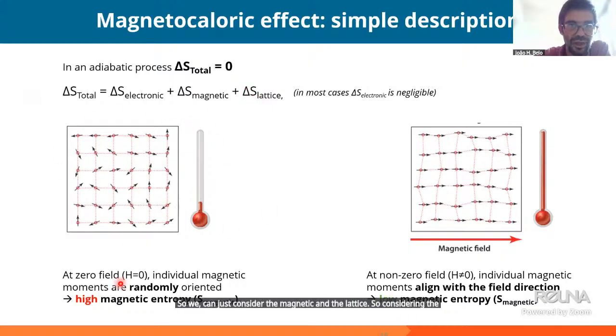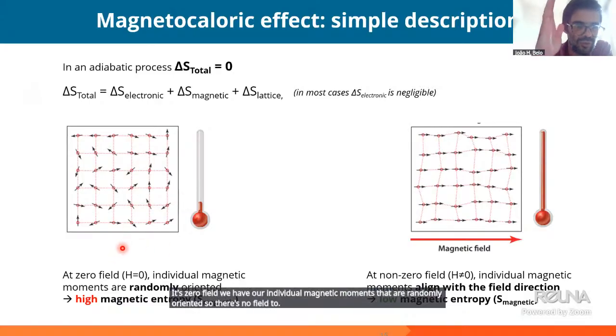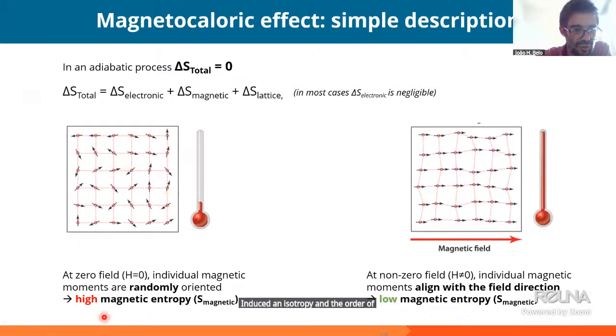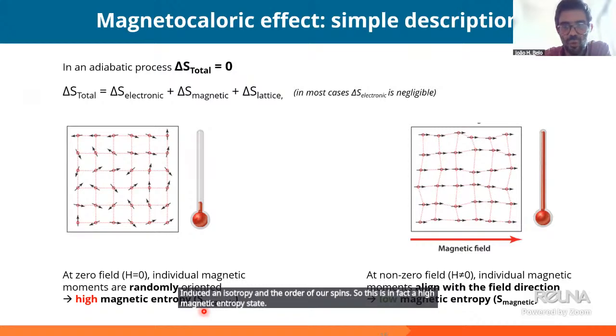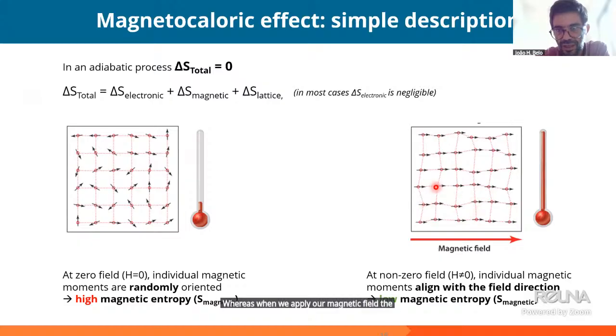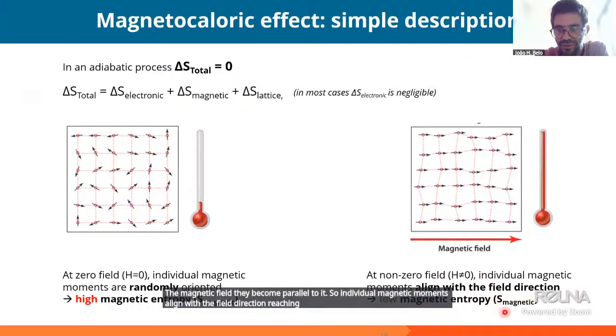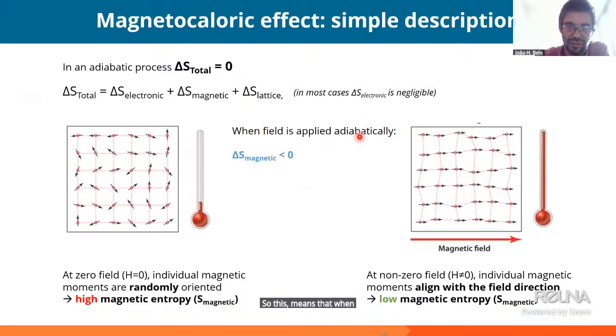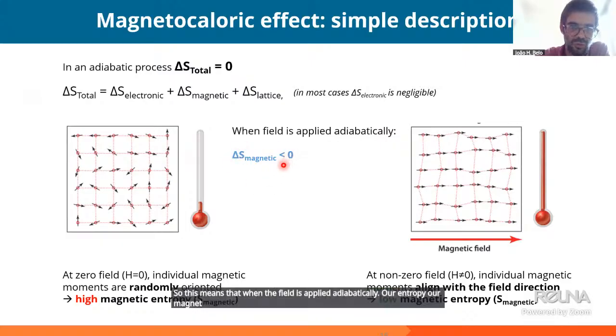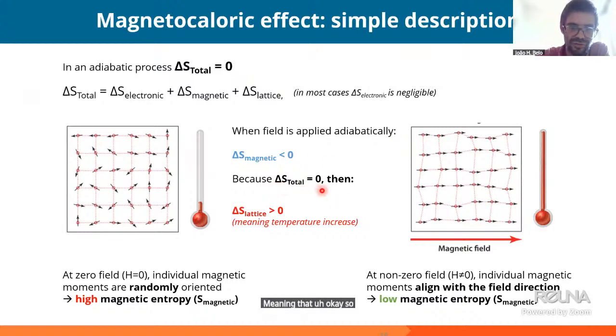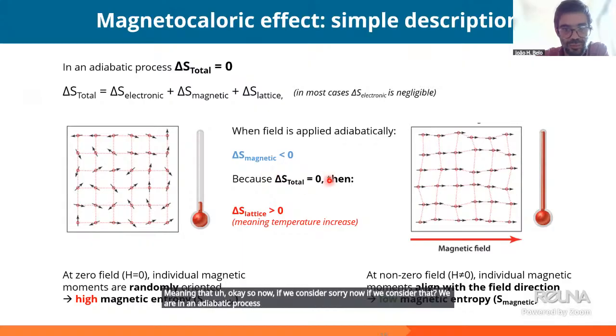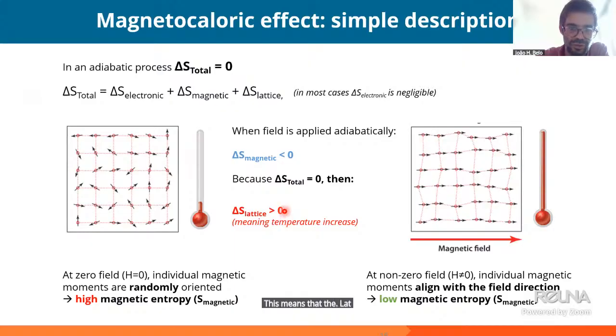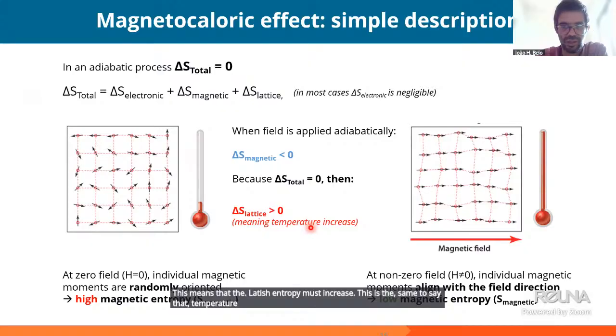So considering the first case, at zero field, we have our individual magnetic moments that are randomly oriented. There's no field to induce the anisotropy and the order of our spins. So this is in fact a high magnetic entropy state. Whereas when we apply our magnetic field, the spins align along the magnetic field, they become parallel to it. So individual magnetic moments align with the field direction, reaching a low magnetic entropy state. So this means that when the field is applied adiabatically, our magnetic entropy is reduced because we go from a high to low magnetic entropy state. Now if we consider that we are in an adiabatic process, the total entropy must remain constant. This means that the lattice entropy must increase. This is the same as saying that the temperature increases in our given material.